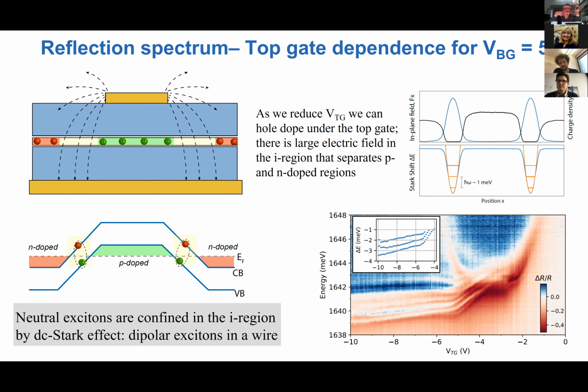But let me say that one interesting aspect of this PIN device is that in principle, one can actually avoid optical doping, because I can think about applying a voltage between the P and N doped regions, a source-drain type voltage. In this case, I would be able to increase the Fermi energy difference between the two layers to about an exciton energy, or one of these 1D exciton energies. And then at this point, one should obtain an electrically injected excitonic condensate. And again, assuming that the temperature is low enough and disorder is low enough, that could be a way of getting a coherent light source.